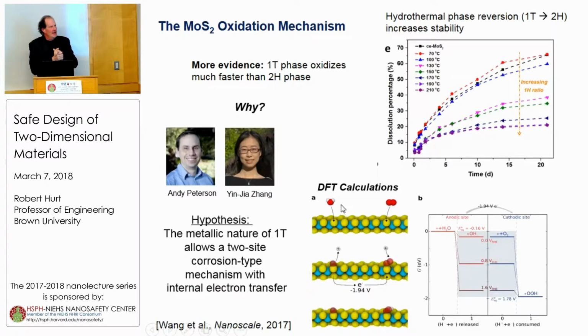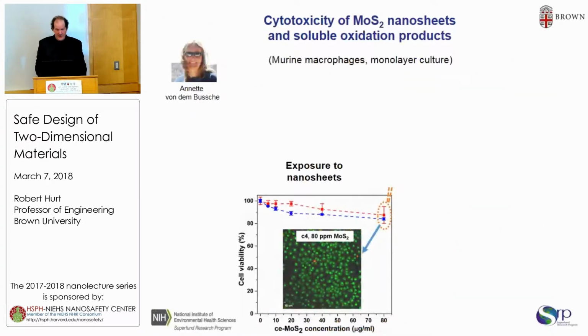What we have done is worked with Andy Peterson here at Brown, who does DFT calculations, and he's developed a hypothesis that the metallic phase oxidizes more readily because it's capable of participating in two-site corrosion type mechanisms. So here's the molybdenum disulfide nanosheet. This is water, and this is oxygen. Water gets oxidized. Oxygen gets reduced on two separate sites. To make this reaction go further, you need electron transfer between those two sites. That electron transfer has to occur through the material. That's only possible with the metallic phase and not with the semiconducting phase. And that is our hypothesis for the behavior of molybdenum disulfide.